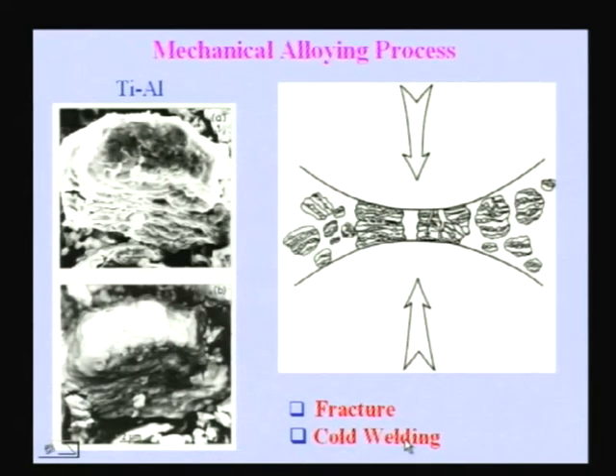When a particle breaks, depending on the type of particle, if it is a ductile particle, it becomes like a flake. Whenever a ductile particle is hit by a ball, it immediately becomes a flake, and that flake, if it comes across another flake, because it has a large surface area to volume ratio, a fresh surface is exposed, so immediately there is a tendency for welding to occur, and as a result you can see here a pancake type of structure, like a sandwich kind of structure. So you can see layered structures.